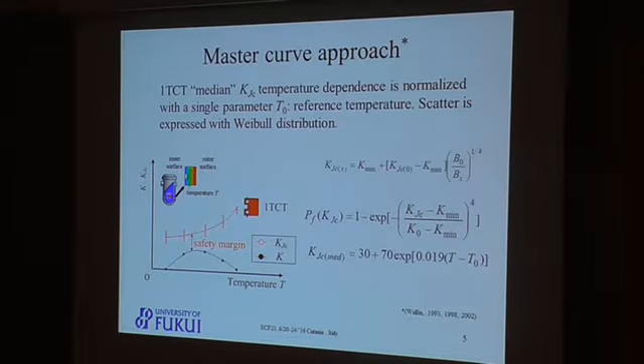One of the widely accepted methods to bypass this test specimen size effect of JC is the master curve. The approach assumes a statistical weakest link model for cleavage fracture and uses a Weibull distribution to express the scatter of fracture toughness KJC. The procedure is based on the concept that a normalized curve of the median fracture toughness for 1T, a 25 millimeter thick specimen, versus temperature is applicable to a wide range of ferritic pressure vessel steels and structural steels. Thus, KJC median was expected to be expressed with a single parameter, the master curve reference temperature T0.